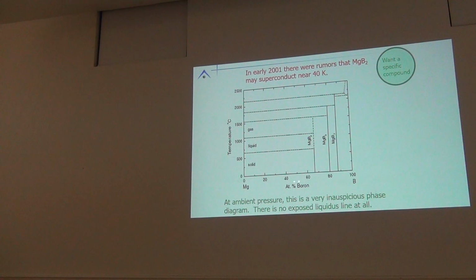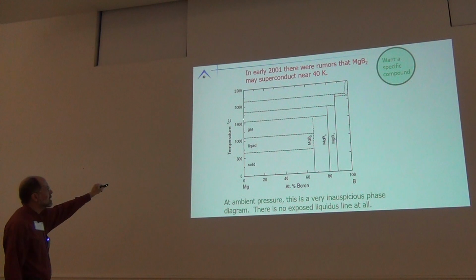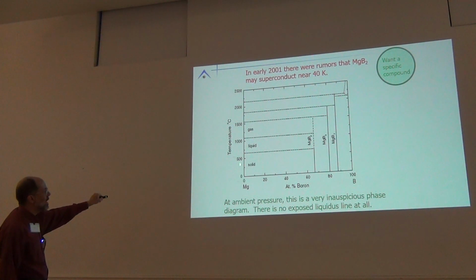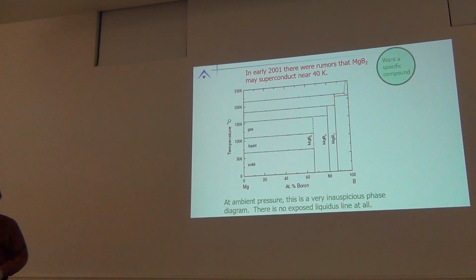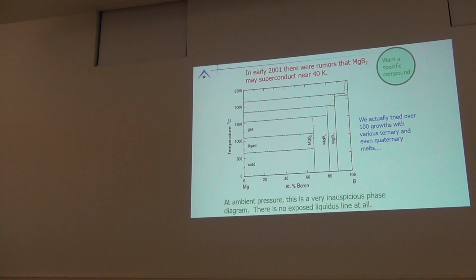Okay. This is the magnesium-boron phase diagram. And unfortunately, after having spent all of yesterday hopefully impressing upon you, if you want to grow a crystal, you find the exposed liquidus line. There is no exposed liquidus line here. Basically, you have MgB2 existing with solid, liquid, and gaseous magnesium with no exposed liquidus. This is inauspicious for single crystal growth. On the other hand, and we tried lots of different ways, that's a different story.